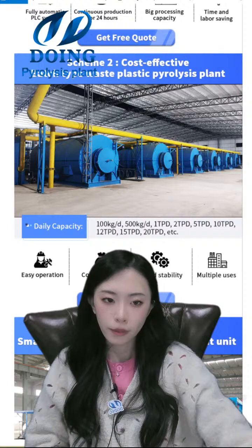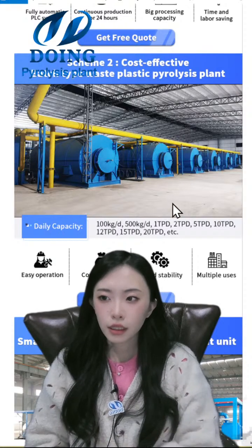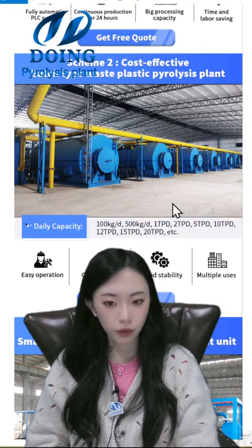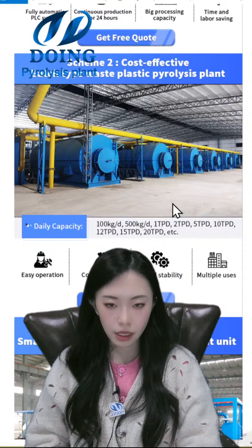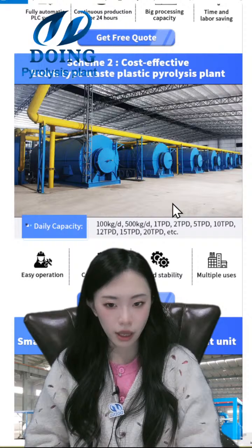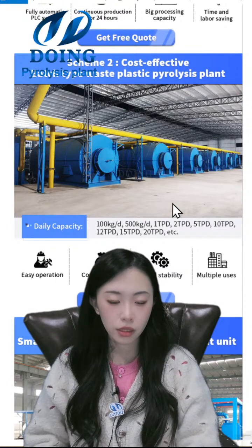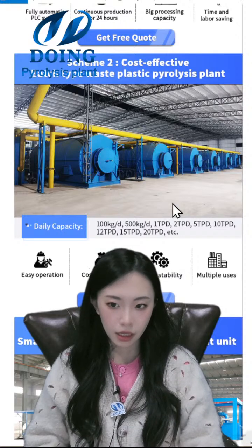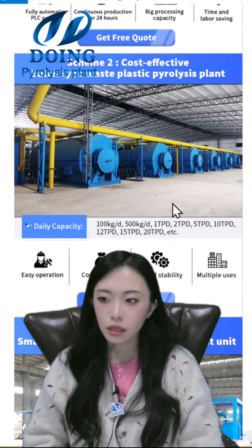And for the working efficiency of the batch type, we can get 1 batch per day. Nearly 20 to 22 hours is 1 batch: 2 hours to feed, and 10 to 12 hours for the pyrolysis reaction, and then also the condensing time and the slagging time. Just before slagging the carbon black, we need to cool down the reactor to a little lower than 100 degrees, so we can ensure it's very safe to discharge. That may take nearly 5 or 6 hours. This is the batch type. We have 1 batch per day.